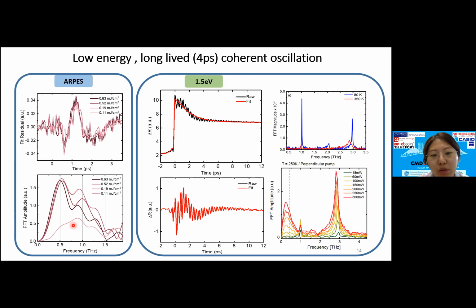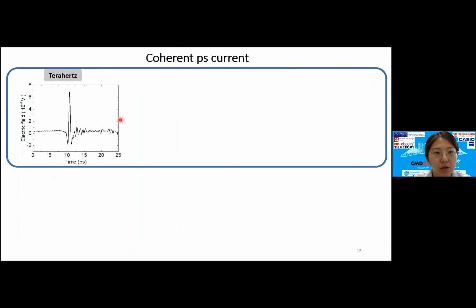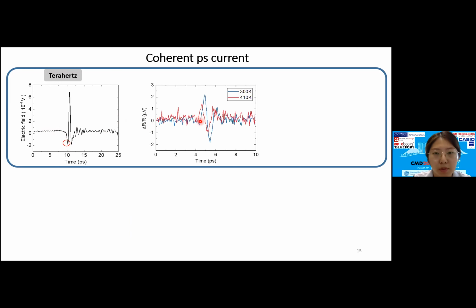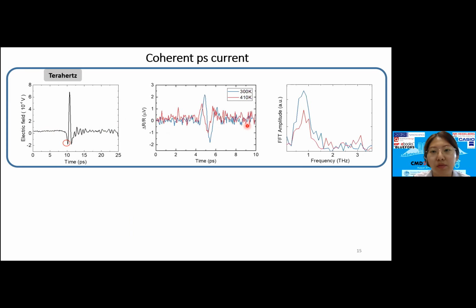The possible interpretation of this polaronic mode is a coherent current, because the line shape of this oscillation is reminiscent of a broadband terahertz pulse. If this is a coherent current, we should see this oscillation in the terahertz range. So we tried to measure optical pump terahertz probe, and this EOS sampling field is reflected from the sample. The dynamics after the optical pump shows this single-cycle-like oscillatory behavior, even below the TC and above the TC.